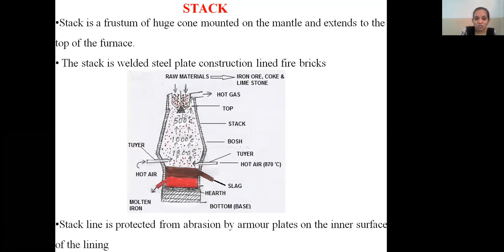So to avoid the erosion of the refractory lining in this stack zone, it is protected from abrasion by armor plates. Armor plates are assembled inside the surface of the furnace lining. Okay, this is about the stack, a frustum of a huge cone. Here we will maintain minimum temperature around 200 to 900 degrees Celsius. It is constructed with fire bricks, and it is saved from abrasion with the help of armor plates.